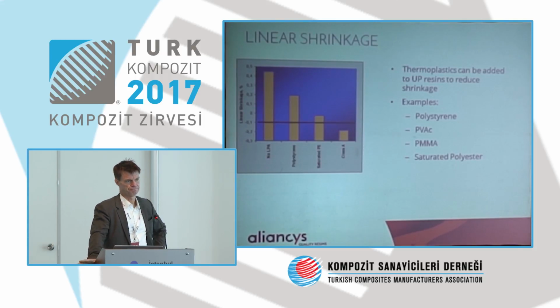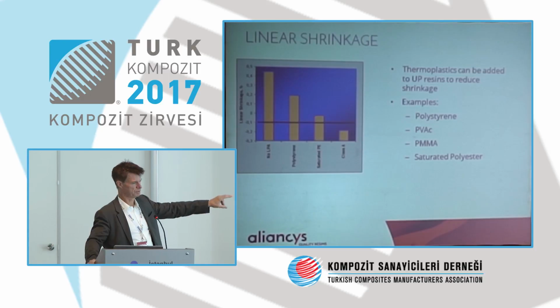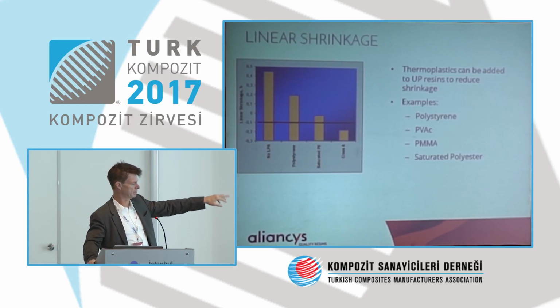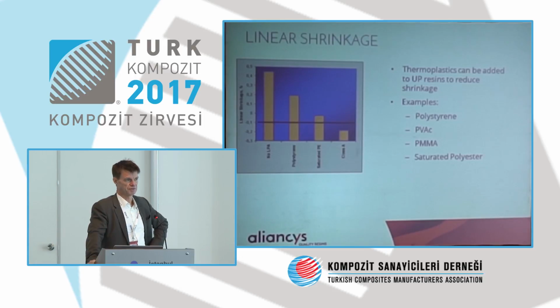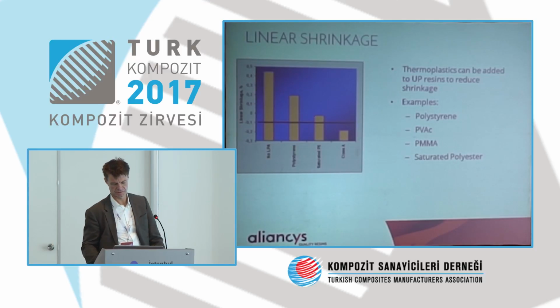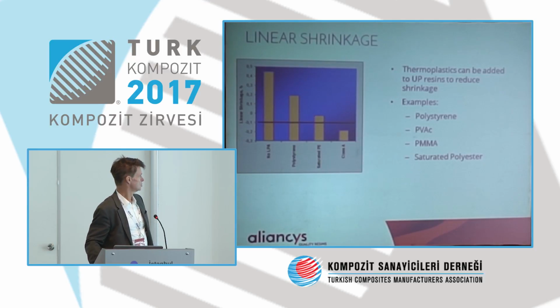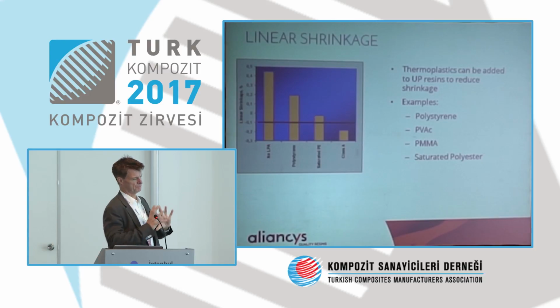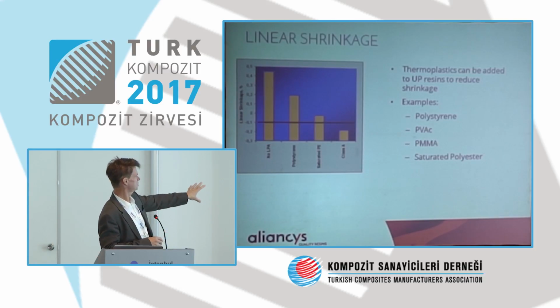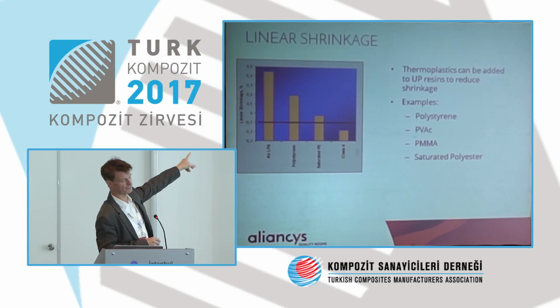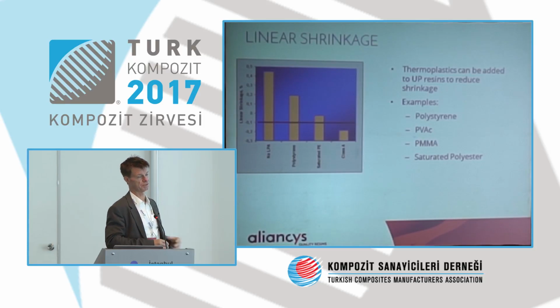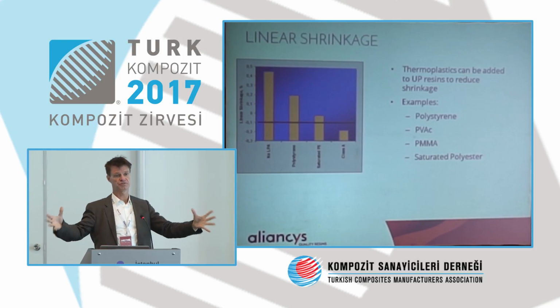But moreover, for better surface quality, you would start to use the saturated polyester. This is the highest performance you can get for the time being. Or something in between, where we do a kind of mix, with products we call modified saturated polyesters. And then we come to a segment where we can use this exactly. So you see, typically per definition, you have shrinkage in a standard material where no LPA is used. You have a shrinkage of about 0.4%, 0.5% in linear shrinkage, because the part has to fit somewhere.